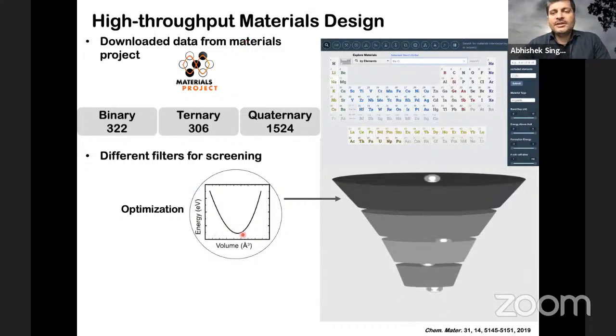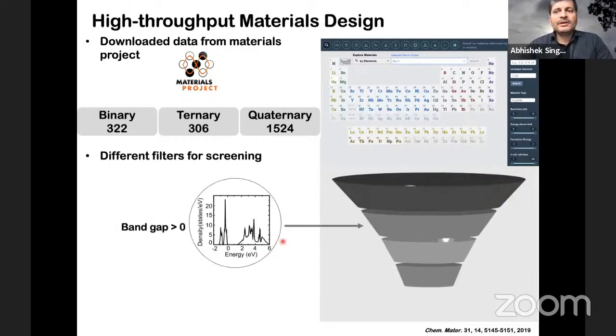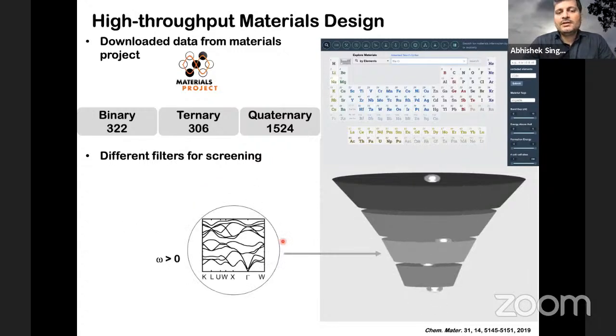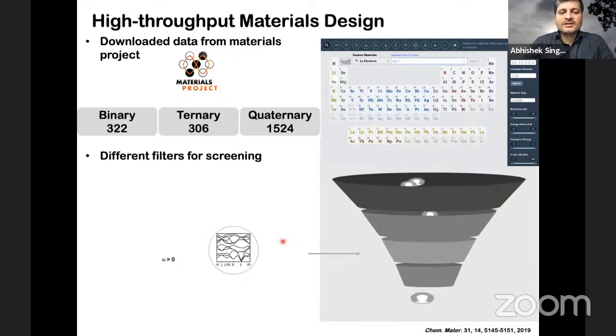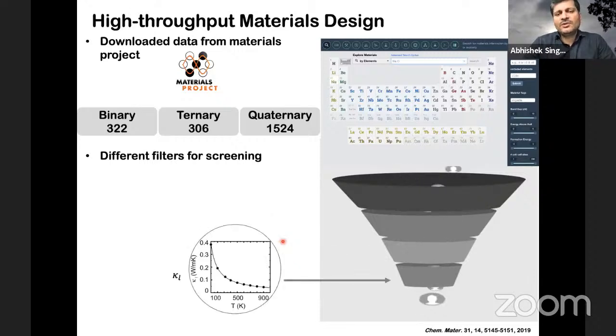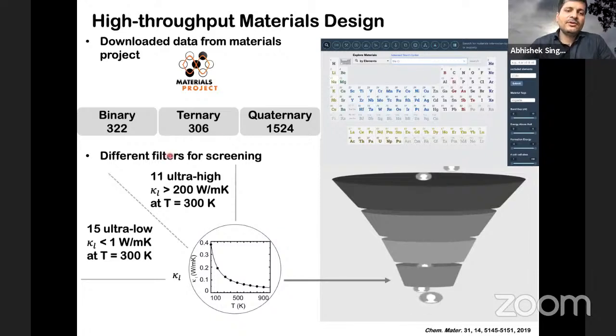Okay, so one thing we did, we optimized the structures. Next, since we were interested in the lattice part of thermal conductivity, we wanted to get only the insulators or semiconductors. So we filtered out all the metallic compounds. Then we also checked their dynamical stability. So we removed all the compounds which were dynamically unstable, and finally we calculated kappa L for about 180 of them. And what we found was about 11 ultra high thermal conductivity materials, with conductivity more than 200 watt per meter Kelvin, and 15 ultra low thermal conductivity materials, which have a kappa L of less than 1 watt per meter Kelvin.